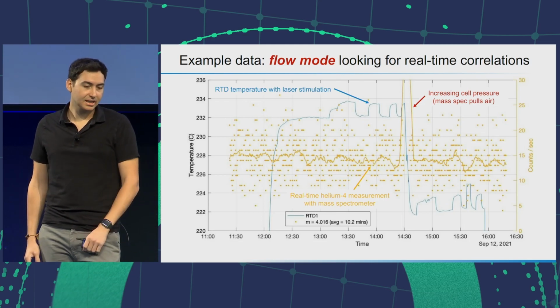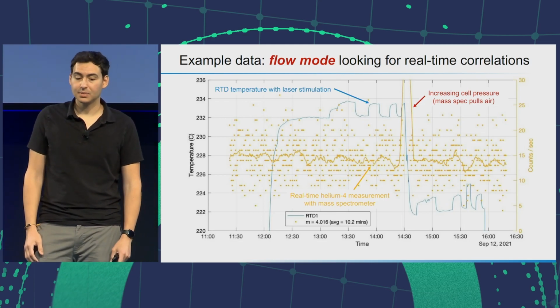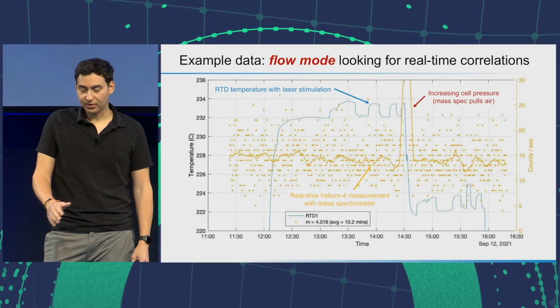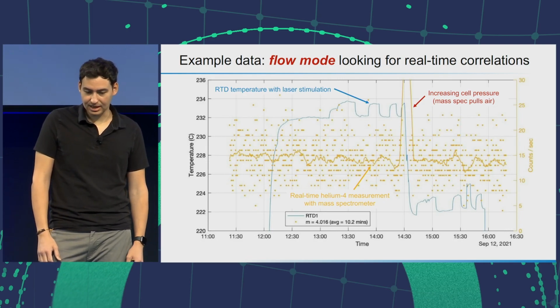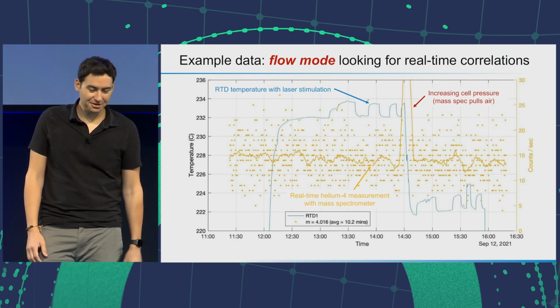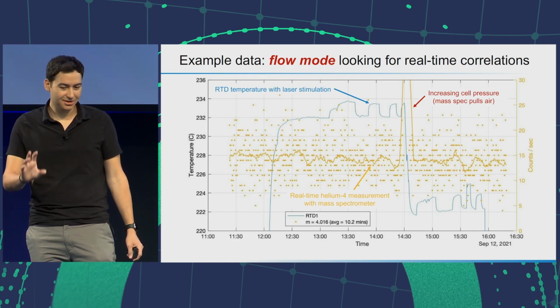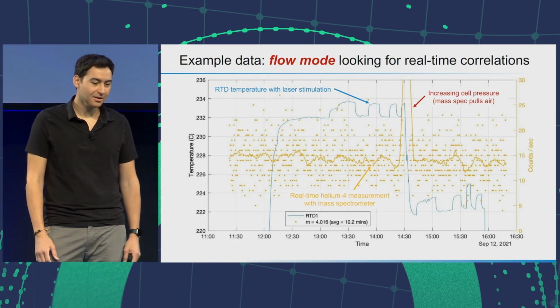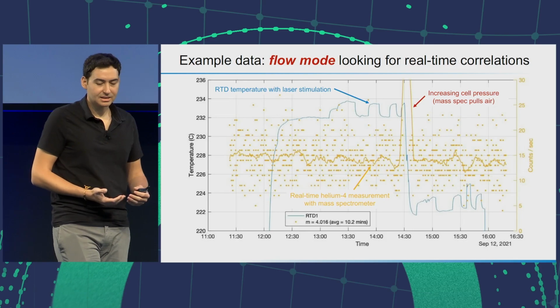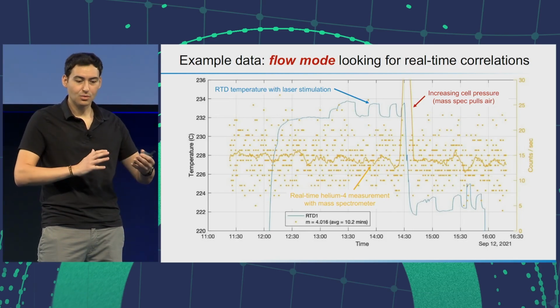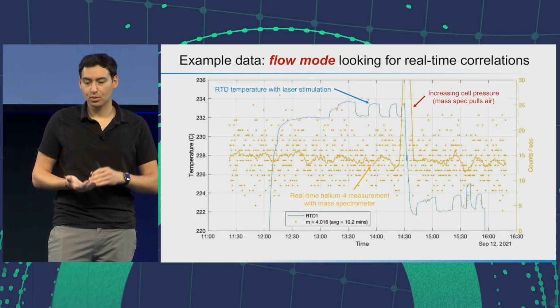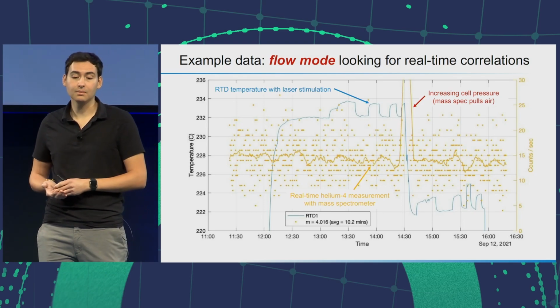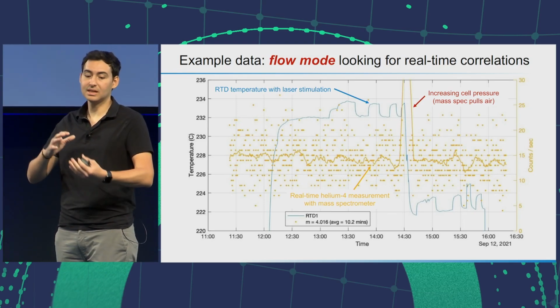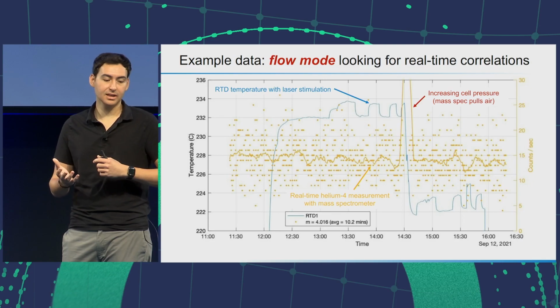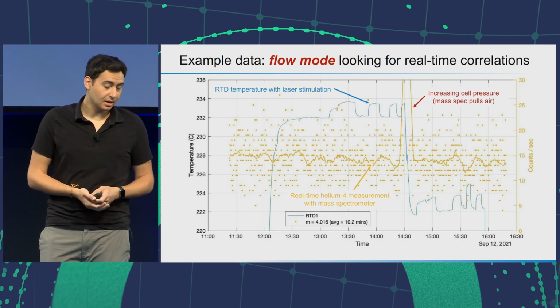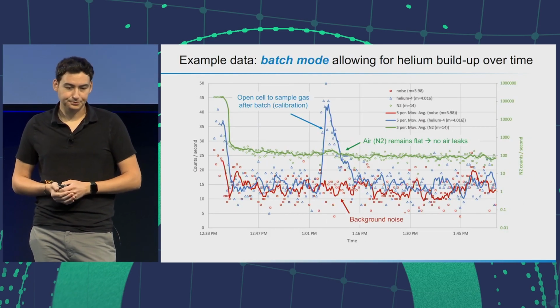And then on the right side is the counts per second of helium, plotted in yellow points here, with a moving average in yellow, the solid line. There was this massive bump here. Unfortunately, that's not an anomalous result. That resulted from the mass spec pulling air. But it's looking at data like this that's giving us confidence in our measurements, that we know when we are getting helium, and importantly, looking at these in real time to see correlations between the indicators, between the stimulation and helium in real time to have confidence in the results.